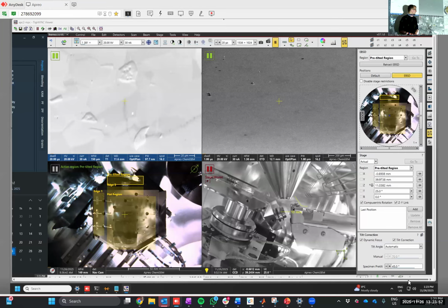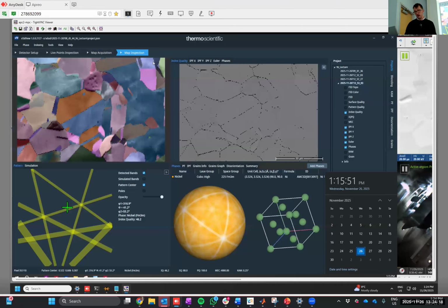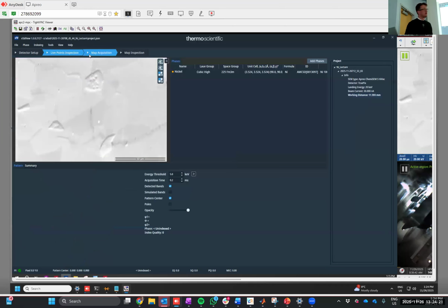This is my EBSD camera inserted. This is my map. It's not hugely in focus because I set it up at 8 in the morning and then didn't get time to realign it just before we started. The horizontal field width here is 150 micrometers in this case. I can then shift to the second screen. Here. And this is my map. This is the software that's running. I've told it that I have some nickel in this. So I've told it from a crystal information file or the standard databases.